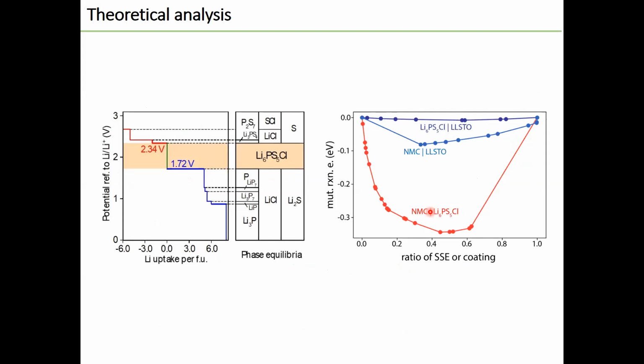Finally, we did a theoretical analysis to study the electrochemical stability window of our electrolyte. From the simulated result, the window is around 1.72 to 2.34 volts, which is consistent with our experimental result. Meanwhile, the reaction energies between NMC and our electrolyte, and between NMC with coating and our electrolyte, were also calculated. There is severe reaction energy between NMC and the electrolyte, while the other two interfaces are much more stable.